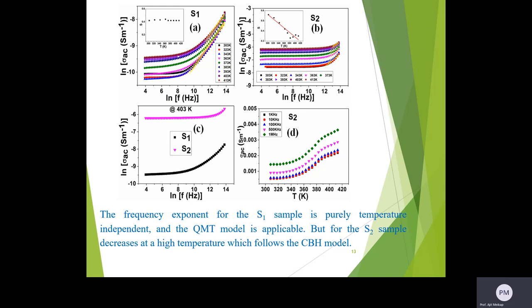For S2 sample it decreases, which follows the correlated barrier hopping model. The conductivity value enhances with increasing temperature, probably due to the enhancement of free charge contribution to the composite system.